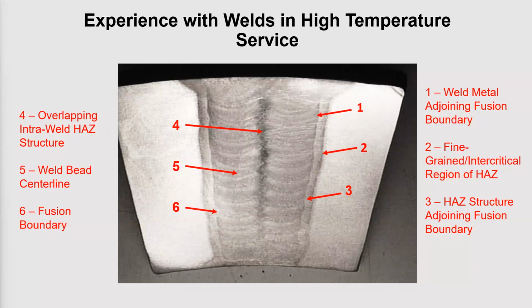Area 4, this is basically a subset of the type 4 region, but it's actually in the weld deposit itself. And it's in situations where you have the kind of stacked weld bead configuration that you can see in this particular weldment, where you created a continuous heat affected zone structure or fine grain heat affected zone structure within the weld deposit itself. Number 5 is showing an area along the weld bead center line. This is not as common, but there have been instances where damage has occurred here. And then number 6 is at the fusion boundary itself.